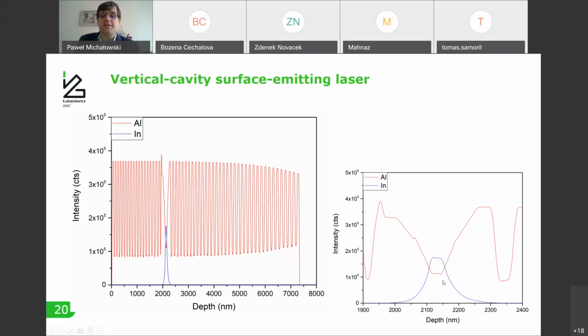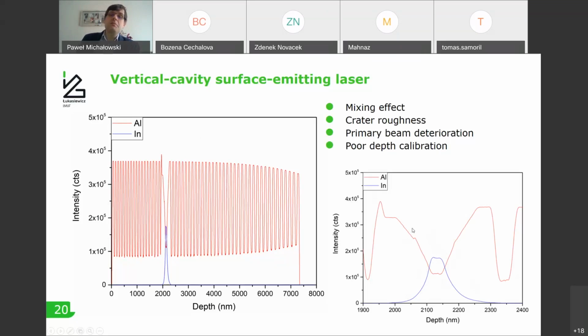There should be 5 of them in here. We can see the indium signal blurred. The problem is the aforementioned mixing effect, causing that for such a thick sample, like 8 microns, the roughness of the crater is also playing an important role. And there is a primary beam deterioration because such an analysis is very long.